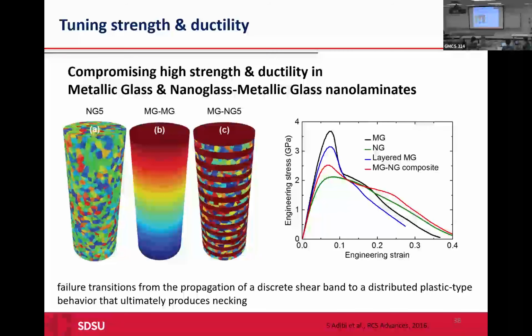One of the other ideas was to combine the metallic glass and nanoglass and make a composite of those, having different layers of metallic glass and nanoglass, just to tune their strength and also their plasticity. These are some of the results that we got for the metallic glass, the nanoglass, and the layered metallic glass, working with the strain and also the ductility of the material.